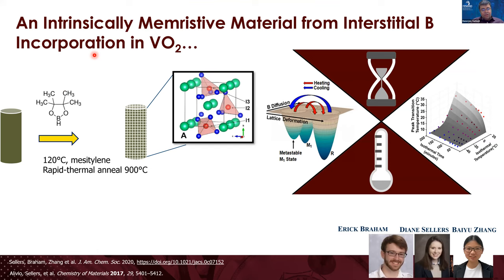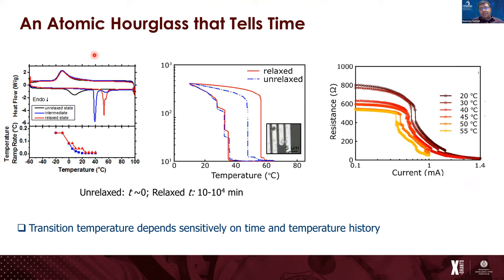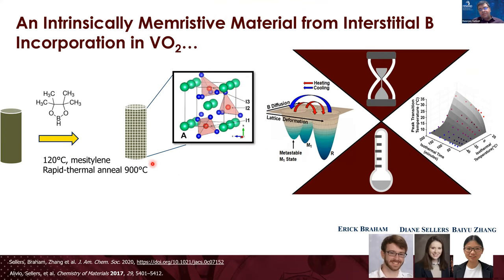I'll tell you about one more. My time is limited, so I'll tell you about one more mechanism that we found that's super interesting. We did some RTA doping of boron. Boron's too small to sit in the vanadium site. Tungsten and germanium sit in vanadium sites, but boron sits in an interstitial site. And here's the interesting thing, the interstitial site where boron sits is different in the two phases of VO2, in the monoclinic and rutile phase.